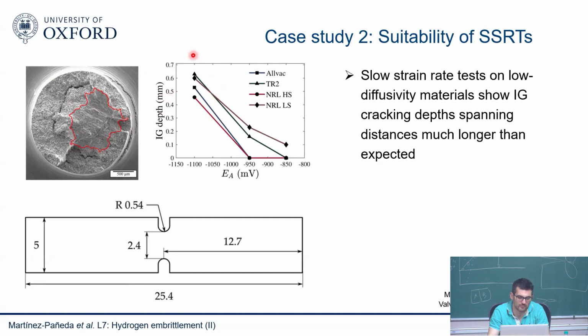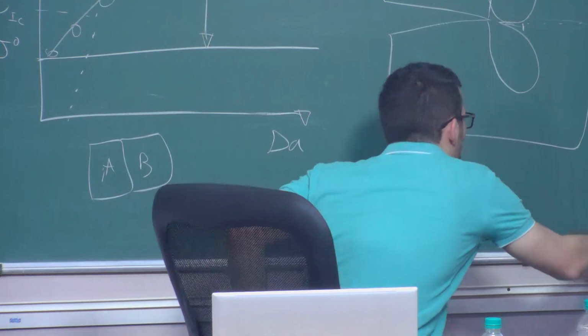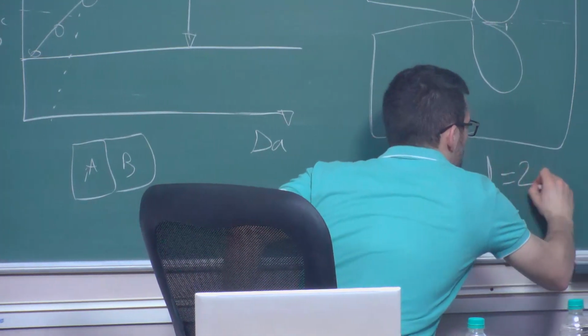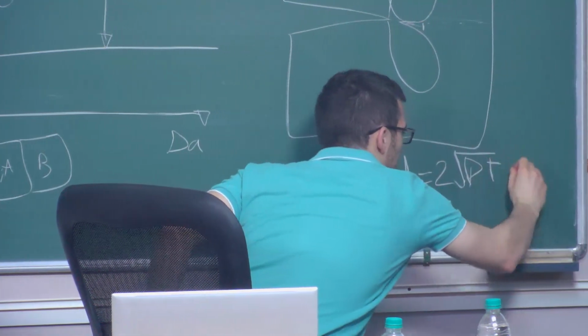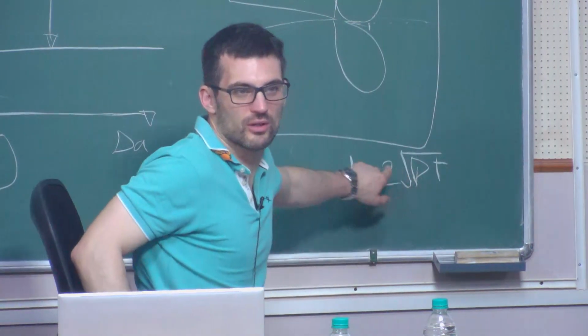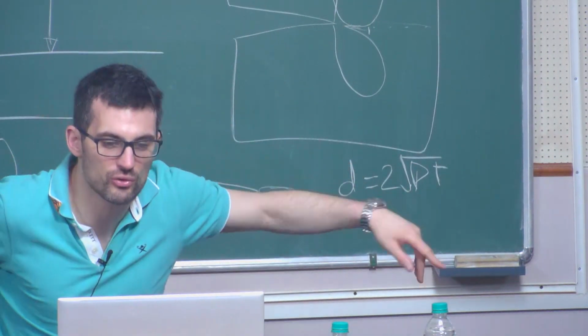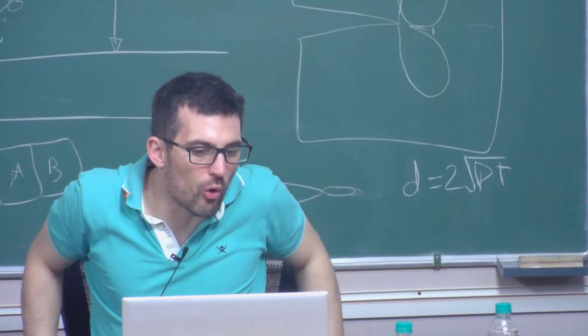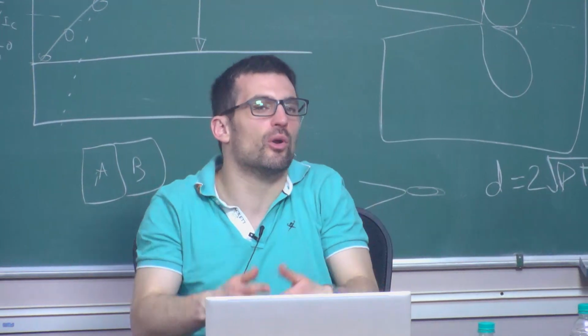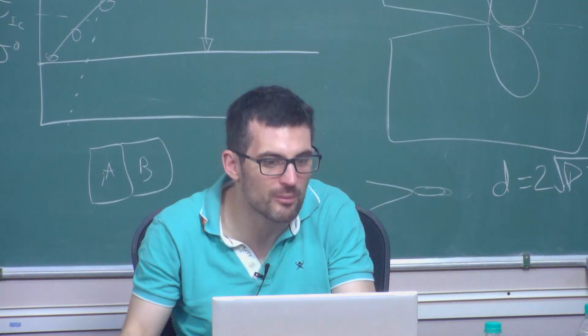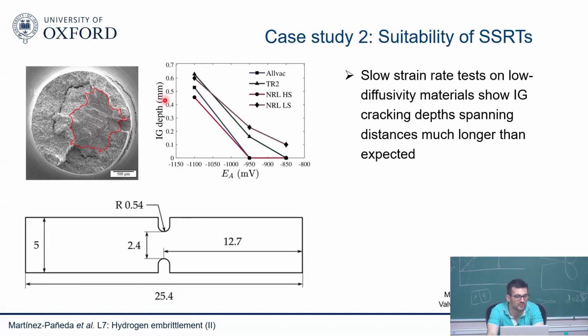So they did some, remember that expression that we discussed before, d equals 2 root Dt. They know the diffusivity of the material, so they know more or less how long the hydrogen has to diffuse. And they figure out that, over the duration of the test, the hydrogen will only move a few microns. So they say, how can it possibly be that we see embrittlement over regions on the order of millimeters? What could possibly be happening there?